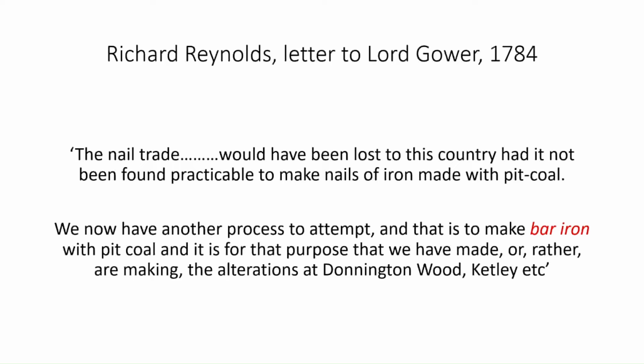And the reason for this was this phosphorus, as I talked about. British ores had lots of phosphorus in them, and that made the iron cold short. It gave them a certain amount of hardness and a certain amount of rigidity, which was fine for making nails and for things that really didn't matter in terms of their mechanical properties. But if you wanted something that was going to be tough and was going to be used for things like chains and the like, then you're going to have to get rid of the phosphorus.